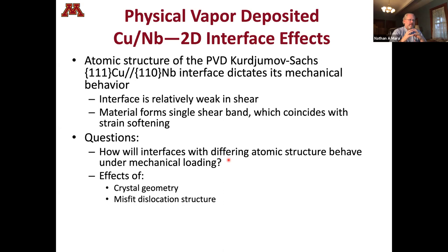So when it sees an elastic modulus mismatch, say you're coming from copper going into niobium, the change in elastic modulus will give rise to what's called an image force. That image force can either aid in bringing the dislocation towards the interface, or it can repel it, depending on what the relative moduli are. This becomes extremely important when we move on to the 3D interface, because now you not only have a discrete difference in the moduli between the two pure phases, you have a mixed region that could have all kinds of variation in modulus across that 3D interface.